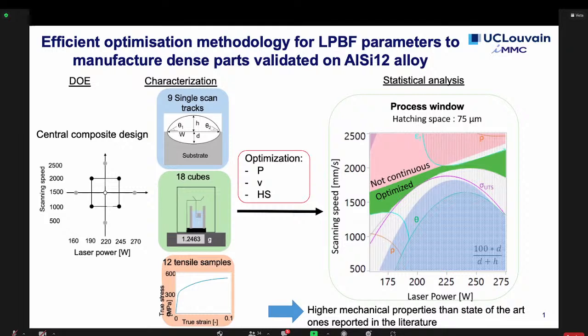We also saw that these mechanical properties were better than the ones reported in the literature. So it's a really interesting methodology to optimize the parameters. We have only used it for the moment on aluminum silicon 12 alloys, but it gave really good results, and we hope we could test it on other materials.